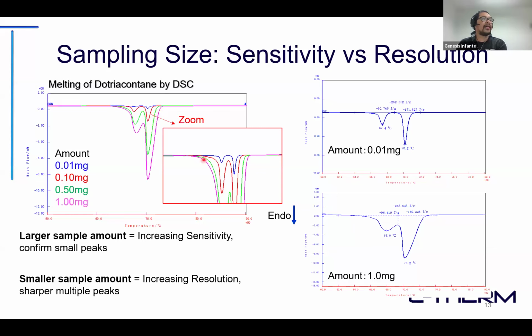But if you want something more refined, let's say the associated energy under this peak, you can see that the energy is about 90.7 and 171.8. And then when you have higher amounts, that value changes a little bit, right? So you want to balance out resolution versus sensitivity when dealing with DSC.